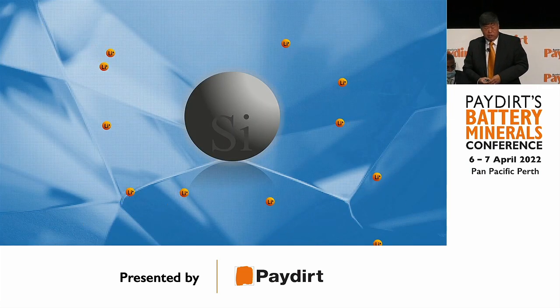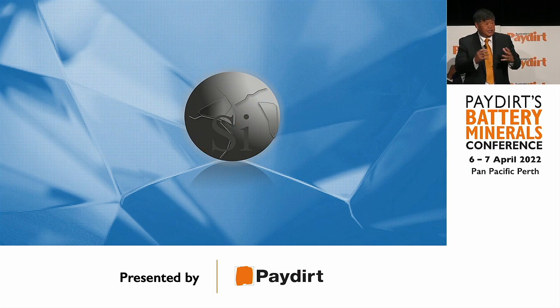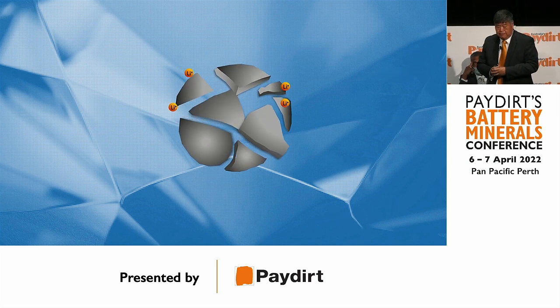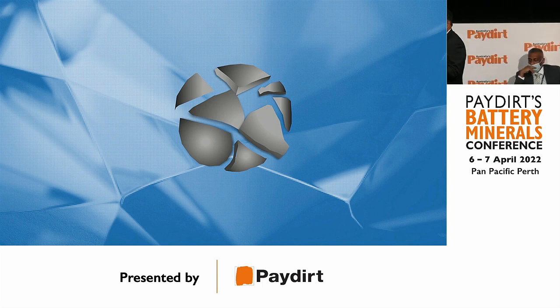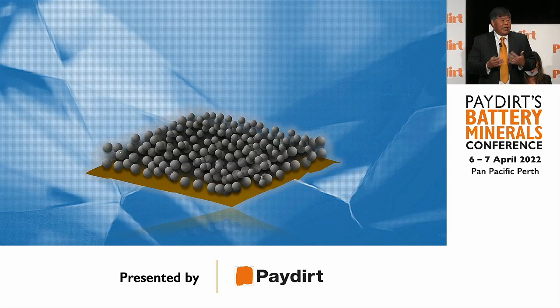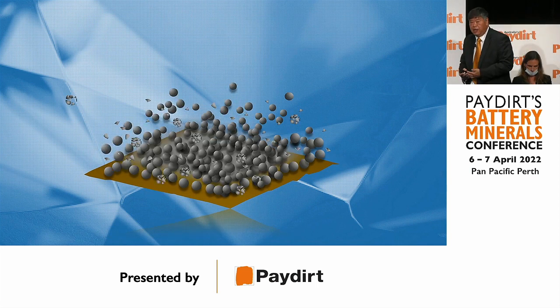The industry has been trying to resolve the 300% volume expansion of silicon particles, which causes fracturing. When a silicon particle in the anode component fractures, you get delamination — the material comes away from the copper collector — and you get swelling in the battery. That is a significant problem.